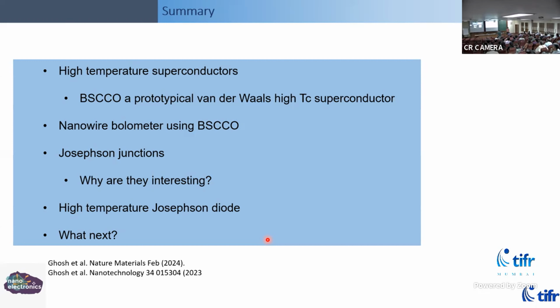So you showed the D-wave symmetry and the twist. So the role of the D-wave symmetry and the twist is ultimately to give the current a unidirectional form. Yeah, the twisting basically, because the current that will go through the Josephson junction is in the D wave, in the, sorry, C axis. And so if I have a D wave symmetry for the crystal, and I have a rotated crystal, the symmetry is rotated by the same angle as the real space twist. So that controls the Josephson junction's properties. But the non-reciprocal response is related to the angle of twist.